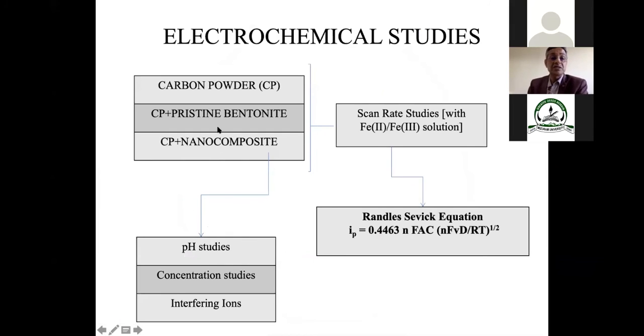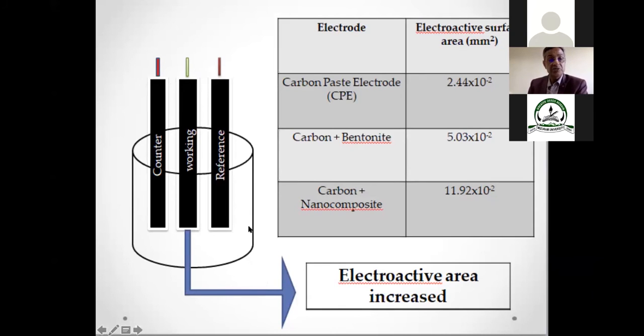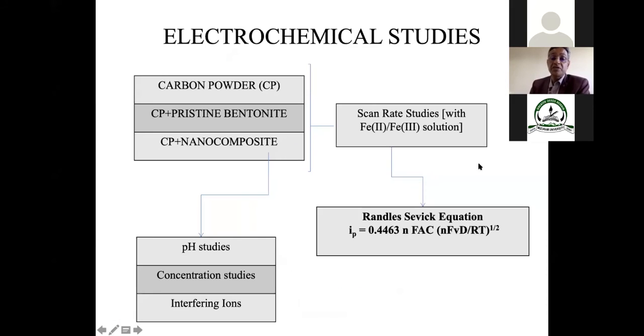So the electrochemical studies that we have conducted with the carbon powder material, and the scan rate studies that we have done with the standard solutions like iron Fe2+ and Fe3+, and the Randles-Sevcik equation, with that we try to calculate, as I mentioned previously, the electroactive surface area. pH studies, concentration studies and interfering ion studies we have done. This is the arrangement of the electrodes: counter electrode, working electrode, reference electrode. The working electrode is the modified electrode. We try to see that the electroactive surface area has increased, calculated with the Randles-Sevcik equation by the scan rate studies.